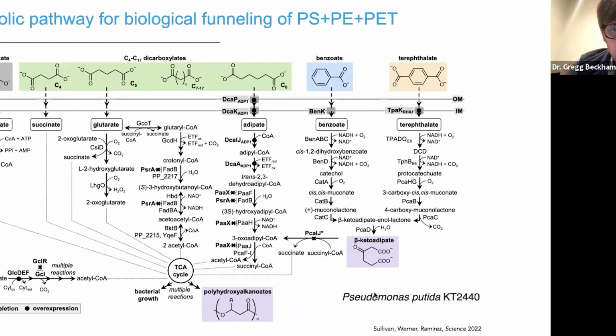So we took an organism, Pseudomonas putida, KT2440. We have a lot of experience with this organism in our group for lignin and sugar conversions from a biorefining perspective. And it natively will consume acetate, which is a residual solvent. It will natively consume benzoate, which is a native carbon source. In previous work, we had engineered it to consume terephthalic acid. And in this work as well, we engineered it to consume dicarboxylic acids. And we made two different products. We have two separate strains.